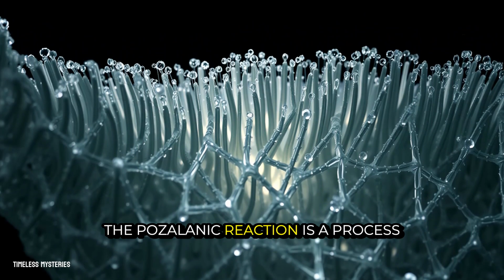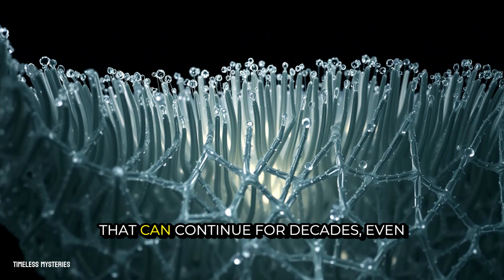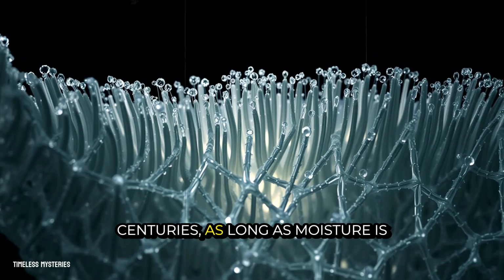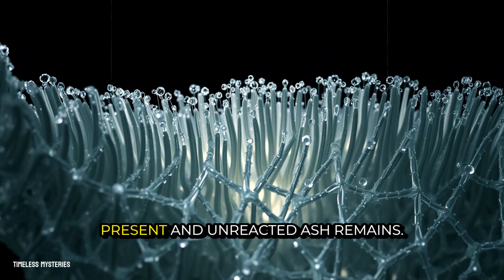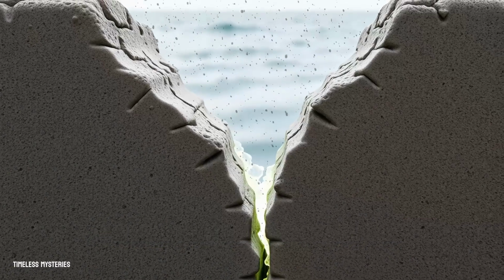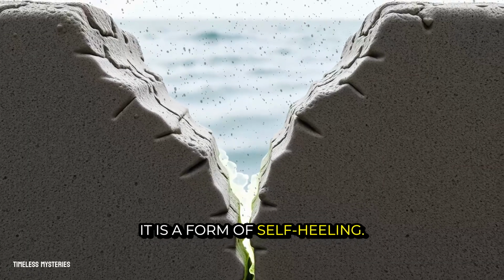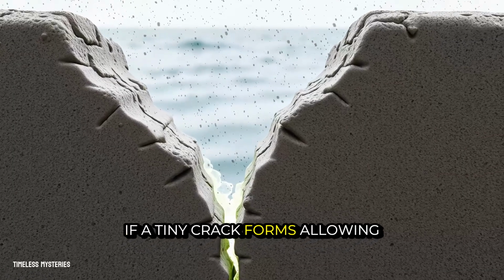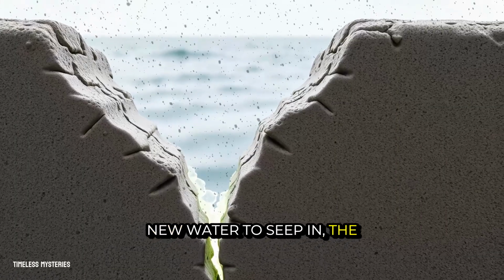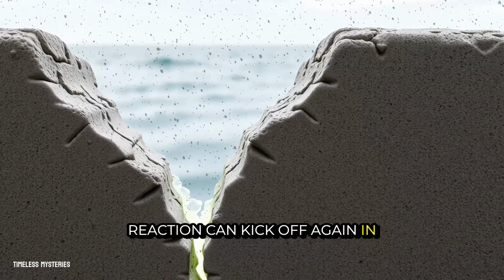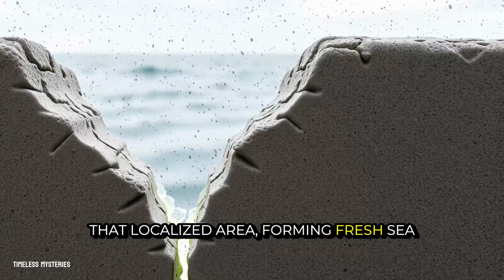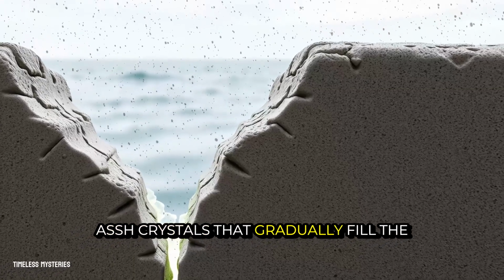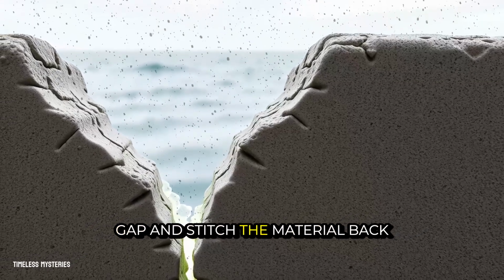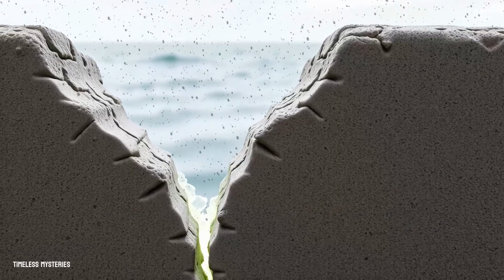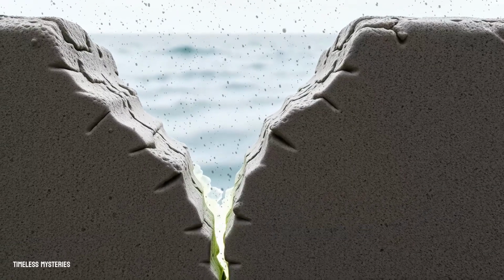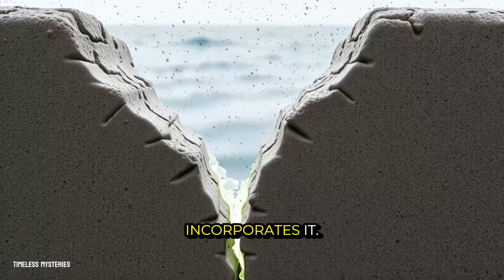The pozzolanic reaction is a process that can continue for decades, even centuries, as long as moisture is present and unreacted ash remains. It is a form of self-healing. If a tiny crack forms, allowing new water to seep in, the reaction can kick off again in that localized area, forming fresh C-S-H crystals that gradually fill the gap and stitch the material back together. This is why Roman concrete does not just resist the sea, it incorporates it.